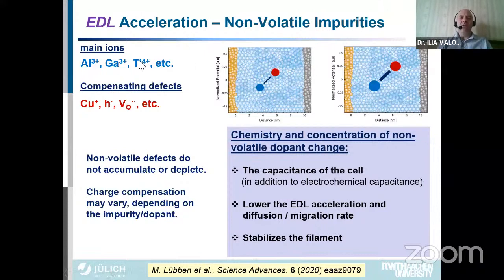What is specific for the immobile ions? They are forming bonds with the mobile ions. For example, if you use gallium or aluminium, they form different bonds to copper, and depending on this, copper will diffuse faster or slower. So this is the main importance of doping or of impurities, that they determine how fast the ions will move compared to the undoped matrix. Doping ions or impurities change the classical capacitance of the cell, because they form dipoles, but also they can change the acceleration effect and diffusion and migration rate, because they hold the ions more strongly. On the other hand, as you'll see, they stabilize the states, they stabilize the filament.